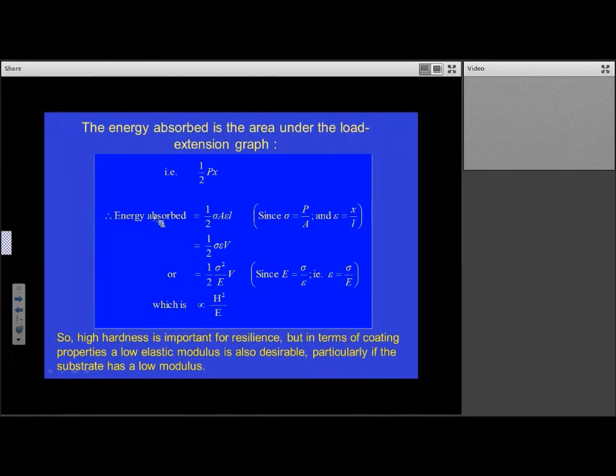Now, because that energy is half P X, and we know that sigma is P over A, force over area, and epsilon, the strain, is equal to the extension over the length, you can actually transpose this, and it turns out that the energy absorbed is sigma squared over 2E times the volume. The energy absorbed per unit volume is half sigma times epsilon. And that's the elastic resilience, which is a well-known parameter. And again, since the maximum sigma is related to the hardness, we see here that the ability to absorb energy elastically is related to H squared over E. So again, another reason why the H over E ratio is important.